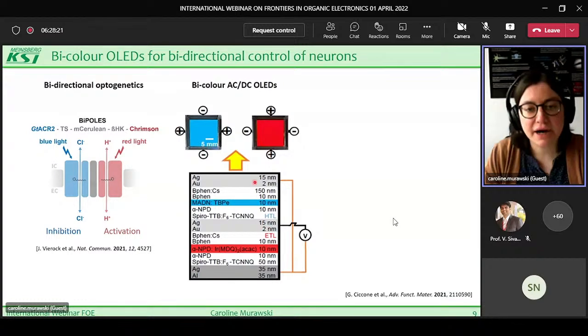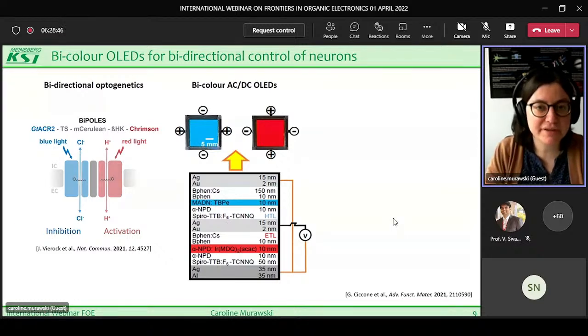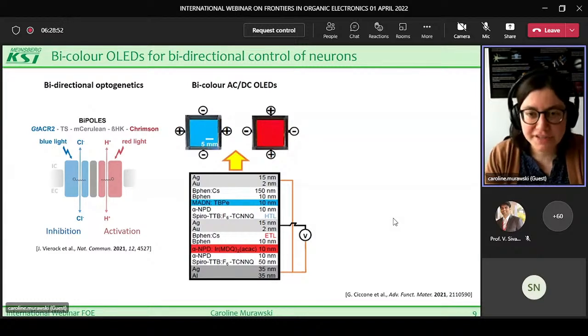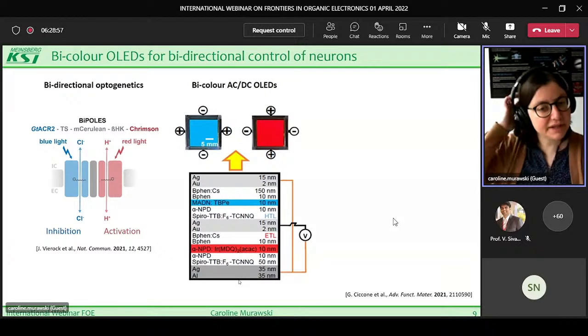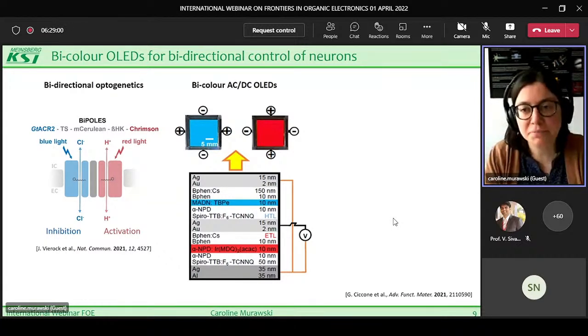And we put the outer 2, this one and this one, onto the same potential. So this means we can either drive this unit by applying positive voltage here, negative voltage here, or if we reverse the bias, have positive voltage here, negative voltage here, then we can light up the blue device. And we can basically switch between blue and red emission in a pretty fast manner. You see that the overall stack is pretty complicated, and especially in top emitting OLEDs, it's very important to consider also the optics of the device.